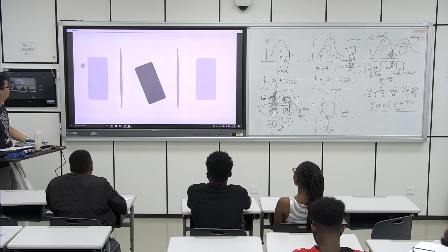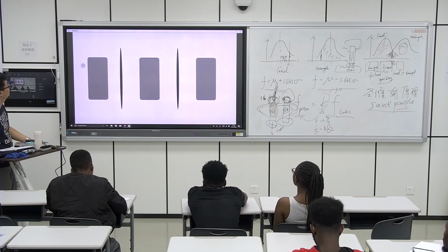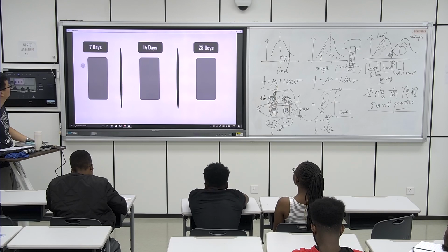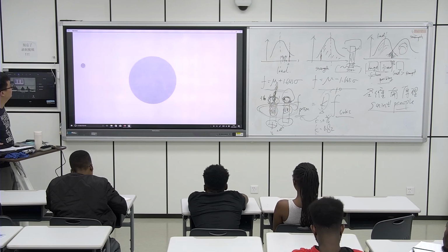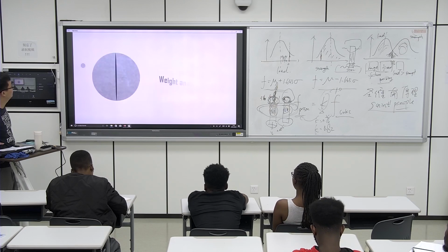Depending upon the requirement, the test specimen is removed from the tank and dried at 7, 14 and 28 days for testing. Draw the line on the specimens as displayed on the screen. Then, record the weight and dimension of the specimen.